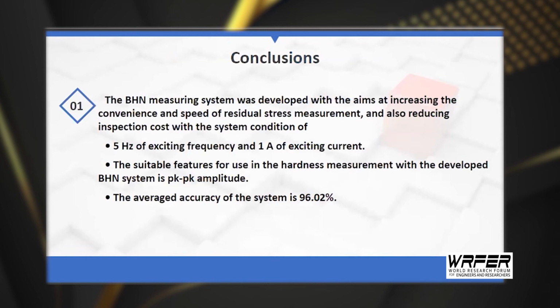To sum up, the BHN system aims at increasing the convenience and speed of residual stress measurement, and also reducing inspection costs. The conclusions of this work are as follows. The exciting frequency and the appropriate exciting current used to measure residual stress are 5 Hz and 1 amp. The accuracy of the BHN system is 96.02% on average when measuring residual stress compared to the XRD technique, which is enough for the steel industry to use as an inspection method for quality control.